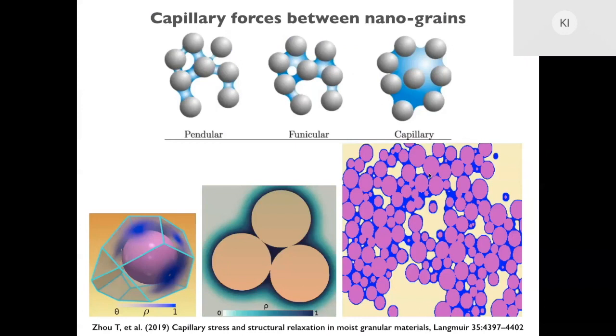How is water distributed in the nanograins of cement? So here in this cartoon on the top, you see what people usually try to model. They model water between grains as capillary bridges. So this is the pendular regime, where one can model this as a spring, an easy way to calculate this type of water distribution. But as we increase the relative humidity, as you can see in the funicular and then in the capillary regime, there are no clear capillary bridges. Basically, the water is forming clusters that are joining all the grains.